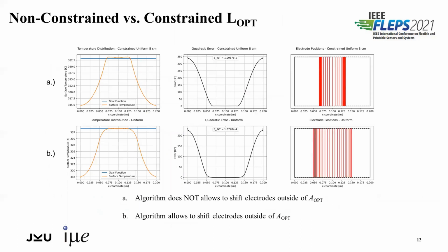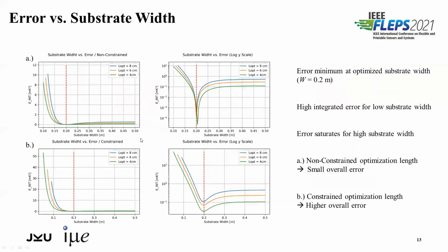This slide shows the difference in the optimization results if A, the algorithm does not allow shifting the electrodes outside the optimization area, and B, if the electrodes can be distributed freely over the whole substrate. Here is an example for an optimization length of 8 centimeter. This could make sense if we want to save space on top of the substrate for other electrode distributions in the neighborhood of the homogeneous distribution. And of course, the integrated error in A is higher if we use this restriction.